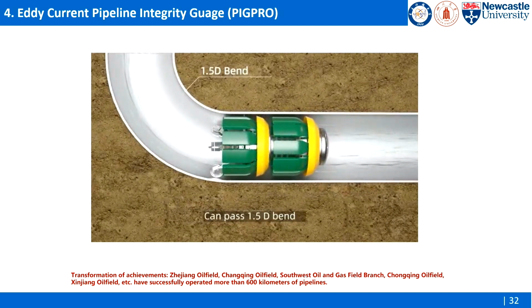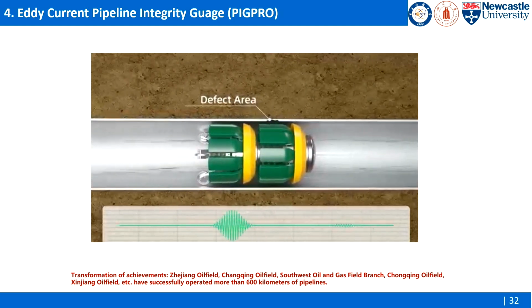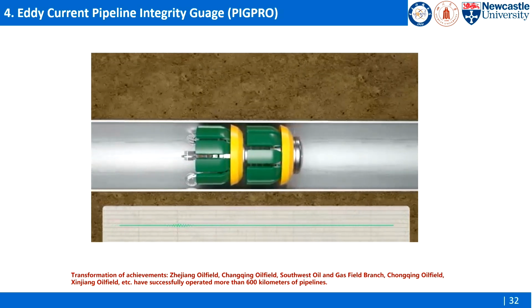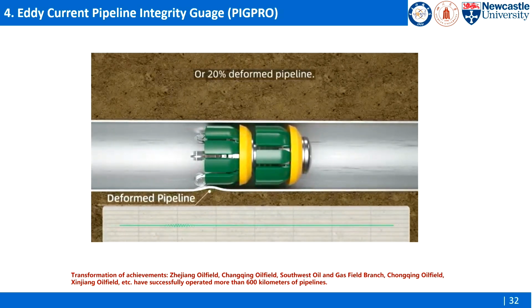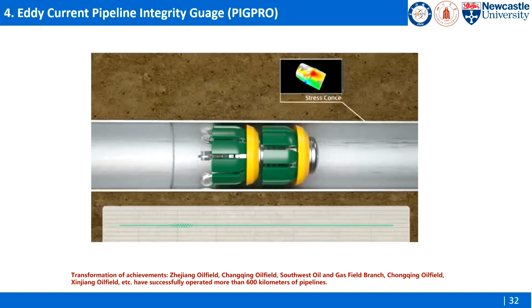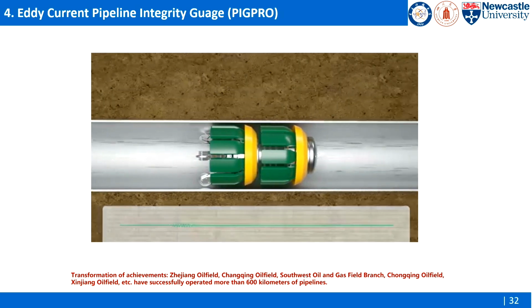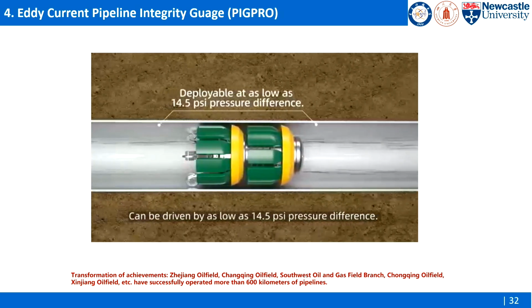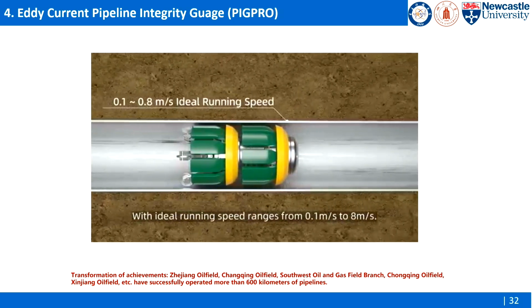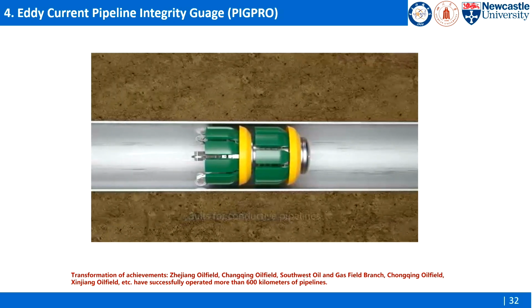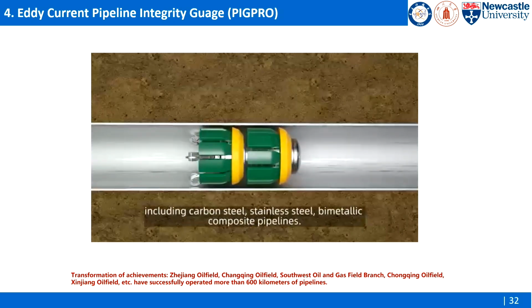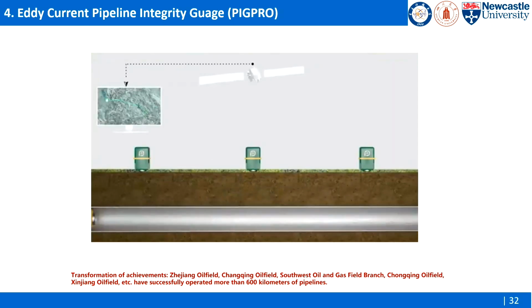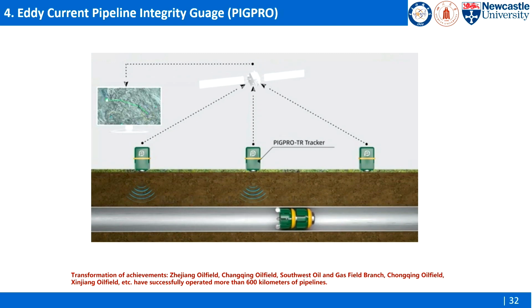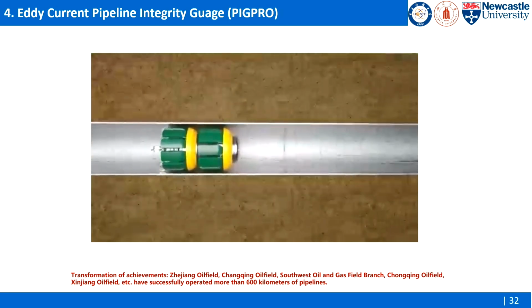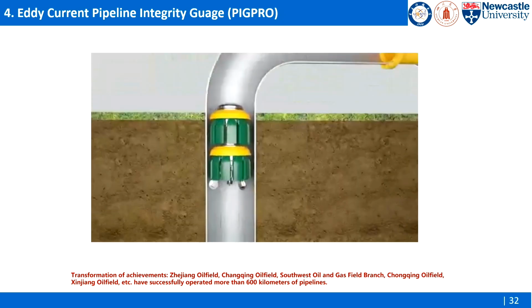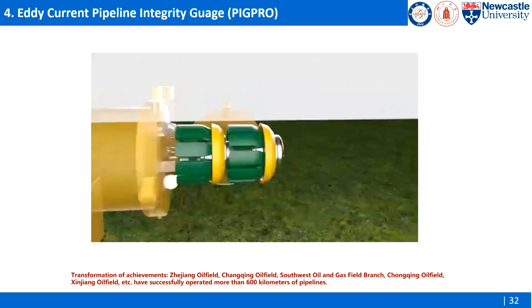Can pass a 1.5D bend, so this kind of portable system can still measure it, or a 20% deformed pipeline. Can be driven by as low as 14.5 psi pressure difference, with ideal running speed ranging from 0.1 meters per second to 8 meters per second. Suits conductive pipelines, including carbon steel, stainless steel, bimetallic composite pipelines. We also can track in the pipe, the pig system, and get the location information. After finishing the inspection, we can take the data out for decision making.